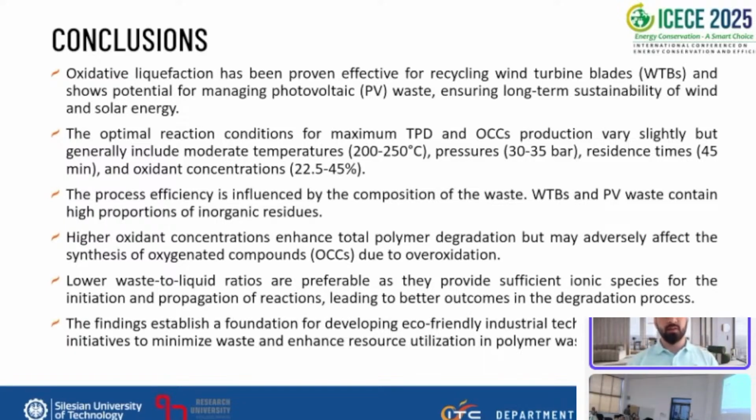Higher oxygen concentration enhances the polymer degradation, but it adversely affects the synthesis of oxygenated chemical compounds due to over-oxidation, and lower waste to liquid ratios are always preferable in the oxidative liquefaction process. This work is, till now, on the laboratory scale, but we are performing some more studies, for example LCA and other estimations, to support its application on the industrial scale.